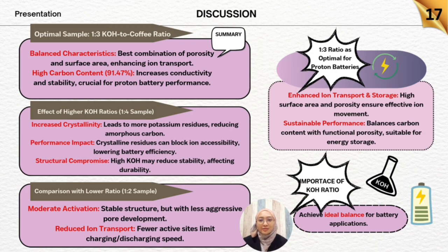Next, effect of higher KOH ratios, which is the 1 to 4 sample. In the 1 to 4 sample, we saw increased crystallinity due to excess potassium compounds. While higher KOH ratios enhance activation, they also produce crystalline byproducts that block ion pathways and reduce conductivity. And comparison with the lower ratio, which is the 1 to 2 sample. The 1 to 2 sample showed moderate activation and a stable structure, but its limited pore development may restrict ion transport, affecting charging speed and efficiency.